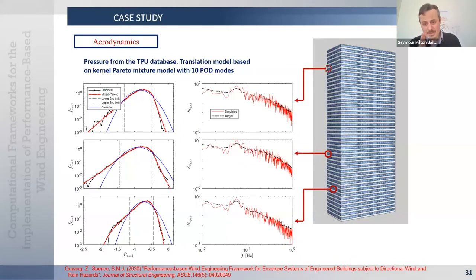On the right, the three plots on the right are looking at the power spectral densities of the pressure coefficients. So in black, we have the targets, that's coming from the wind tunnel data. And in red, we have the spectral densities from the simulated signals. So what we can see is as we move towards the higher frequencies, we are still capable of capturing the energy with 10 spectral modes. So that's just illustrating how 10 spectral modes was sufficient to capture the dynamics of local dynamic pressures in this case.